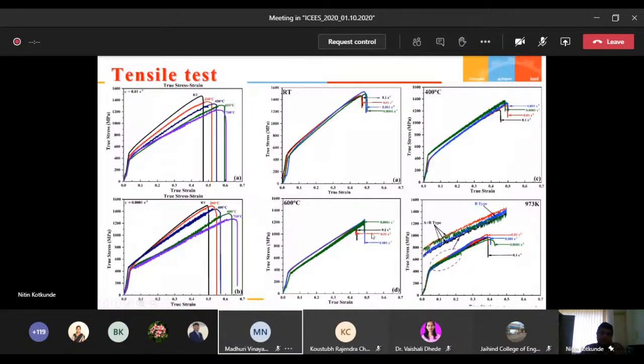If you see here, obviously as temperature increases, the flow stress, or the true stress-strain deformation, or the material properties usually decrease. It means yield strength and ultimate strength are degraded, and percentage elongation increases. If you see here, the effect of variation of strain rate is negligible compared with the effect of temperature. So the strain rate sensitivity, which is a very crucial parameter in metal forming applications, is minimal in the case of Inconel alloy. It means we should not bother much about the punch speed.